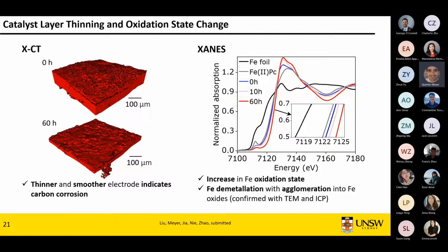So the kind of things we've done was first X-ray CT. We tried to do CT of the same cell. So we sent the samples to Canada, but the problem we had with stability issue was so big that they couldn't operate the samples in an operando cell, because by the time it made it to Canada, the sample was basically already dead.